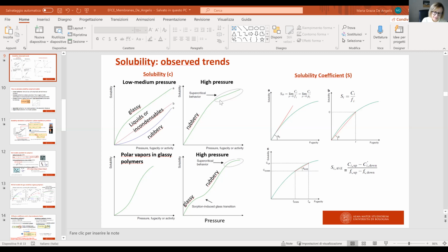One other question is addressed on the swelling behavior. So does this need to be taken into account? Yes, it does. Because especially if you're dealing with CO2 at high pressure, the swelling is relevant. And in the case of a rubbery polymer, you can rely on the equation of state to provide you the correct value of density. But if you are below the glass transition, there is no way to estimate the density a priori. And because the system is no longer following the equilibrium path, it's no longer following what is dictated by the equation of state.